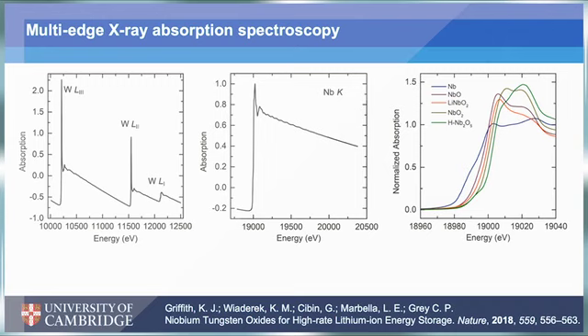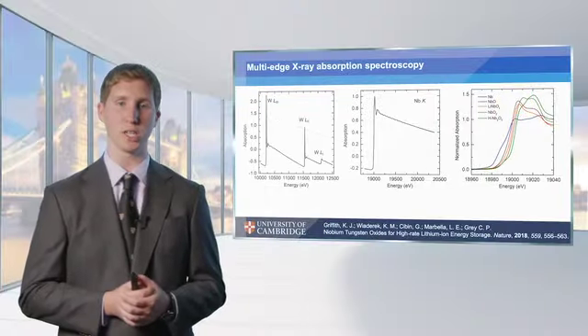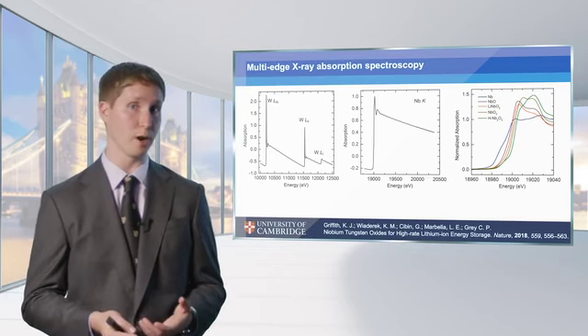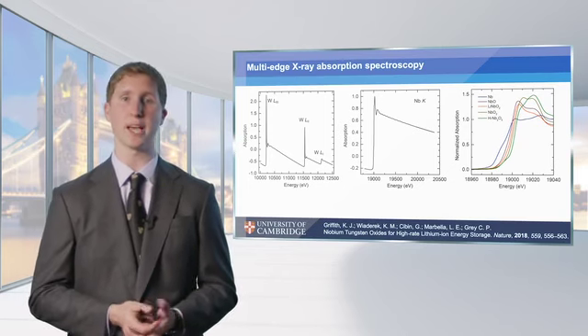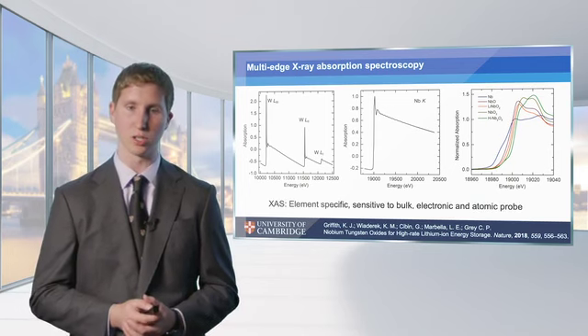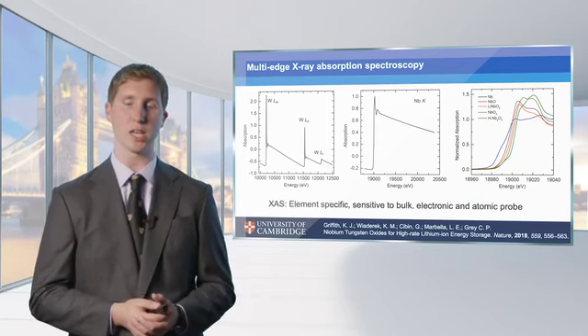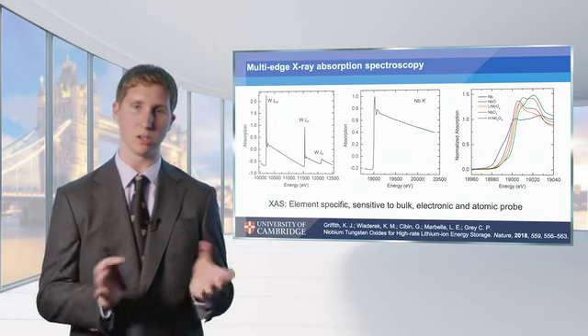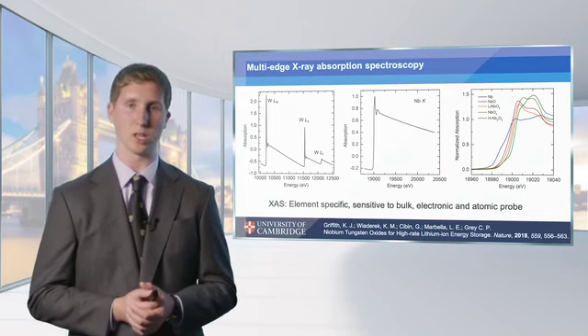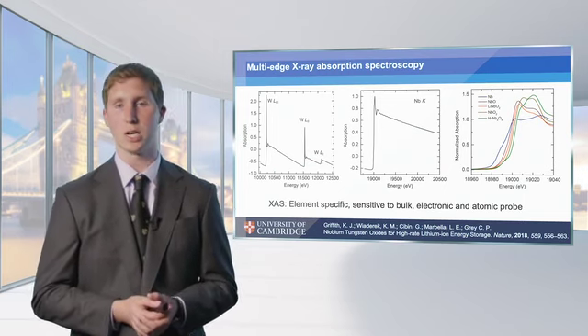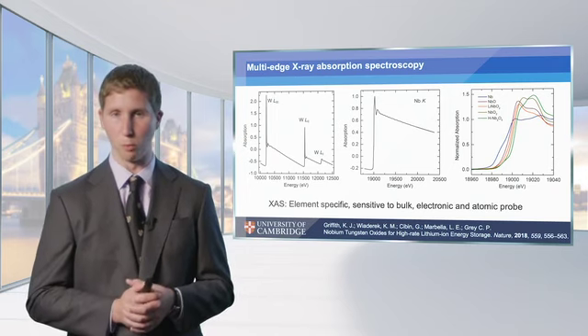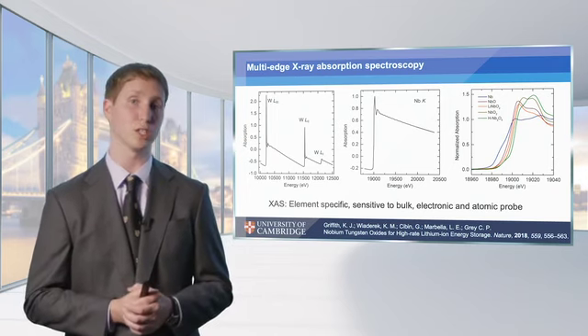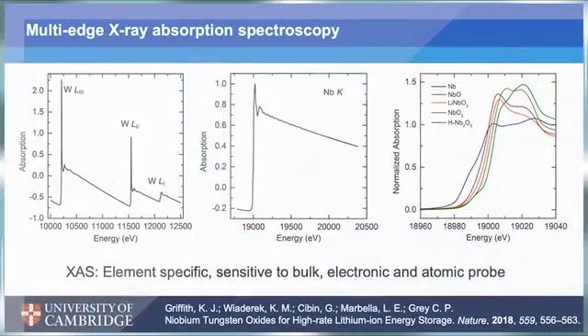And if we are able to map over the niobium and the tungsten individually, as a function of state of charge, we can see which one is being reduced where and which one of them is leading to the excess capacity that we observe in these materials. So XAS is a great element-specific technique that we can discriminate between the performance of these two metals, and we're sensitive to the bulk structure. So we're seeing the whole particle, which complements surface-sensitive techniques. But in XAS, we really want to understand what's going on in the bulk.